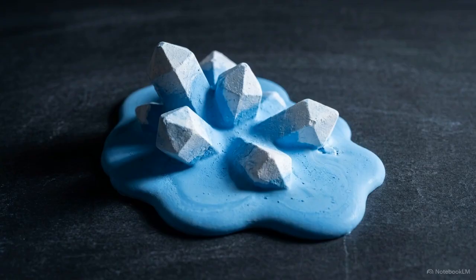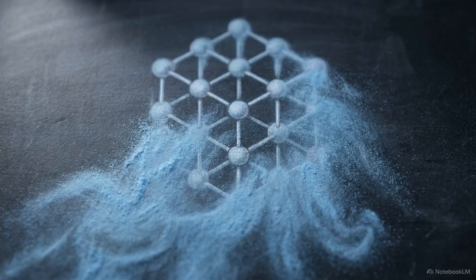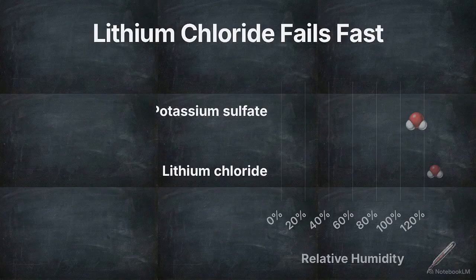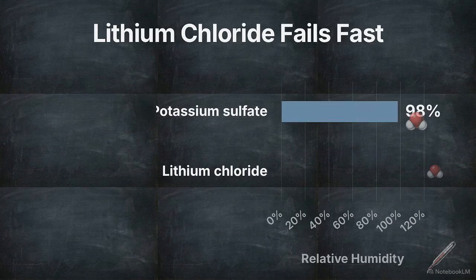In extreme cases, this leads to deliquescence. This is an autocatalytic process where an ambient humidity threshold triggers a solid to literally dissolve into the very water vapor it is absorbing. This table compares the relative humidity thresholds of different salts before dissolution is triggered. Potassium sulfate remains entirely stable up to 98% relative humidity. Lithium chloride, however, fails and rapidly begins dissolving at a mere 13%.